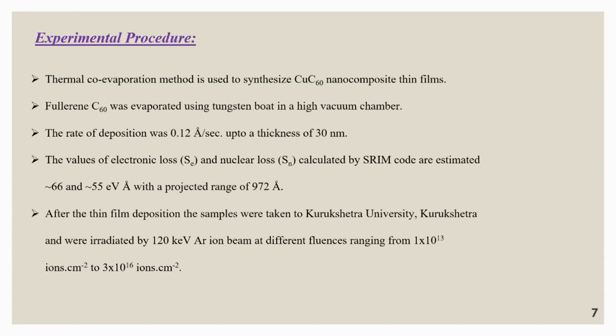So, experimental procedure: we have synthesized CuC60 nanocomposite thin films by the thermal co-evaporation method. C60 was evaporated using a tungsten boat in a high vacuum chamber. 0.12 angstrom per second was the deposition rate, and we have synthesized our thin films up to a thickness of 30 nanometers. The values of electronic loss and nuclear loss were calculated by the SRIM code, which came out to be 66 and 55 electron volt per angstrom, with a projected range of 972 angstrom.